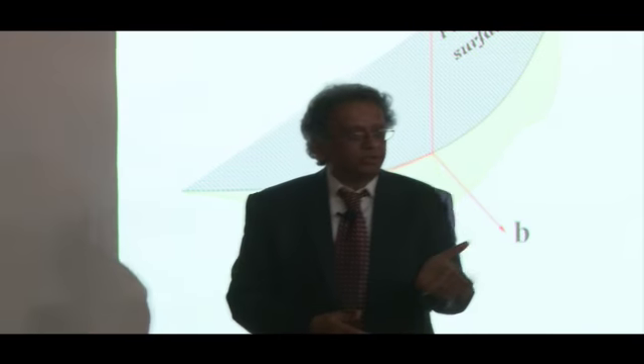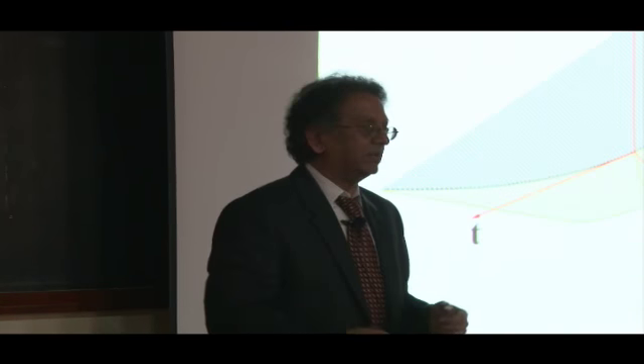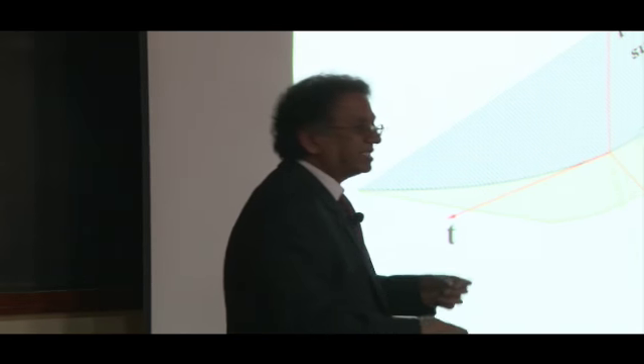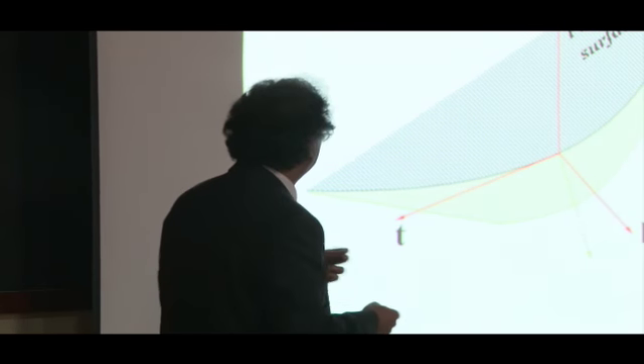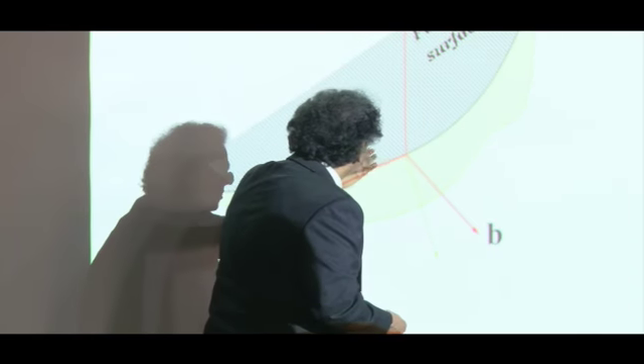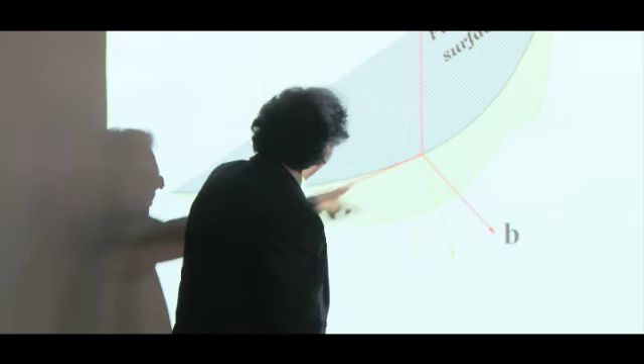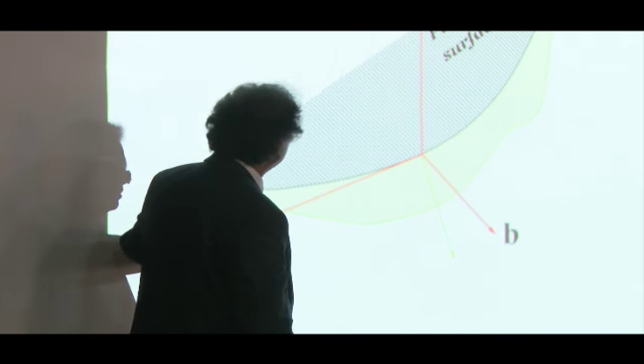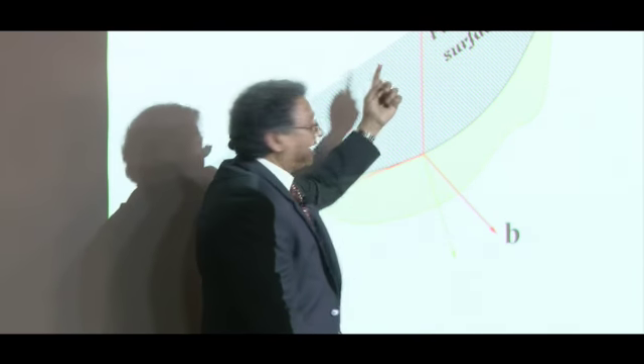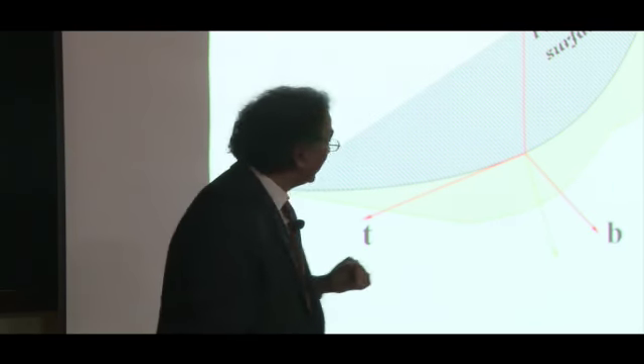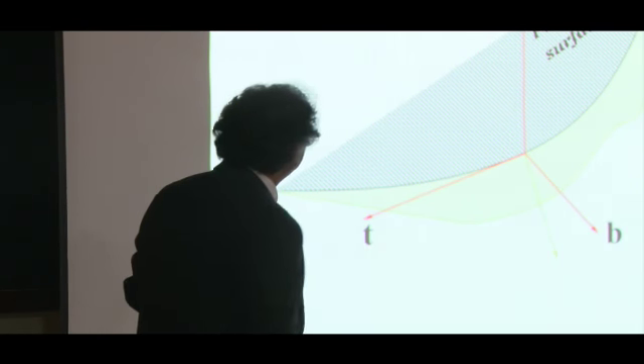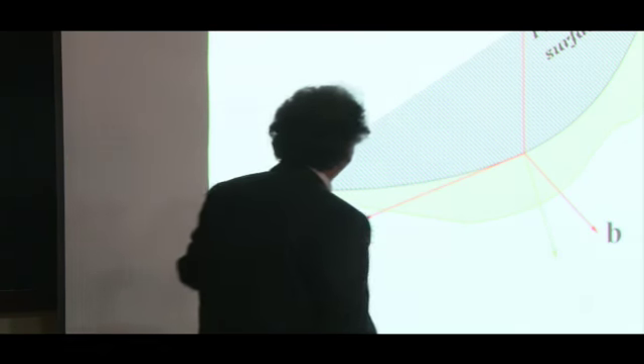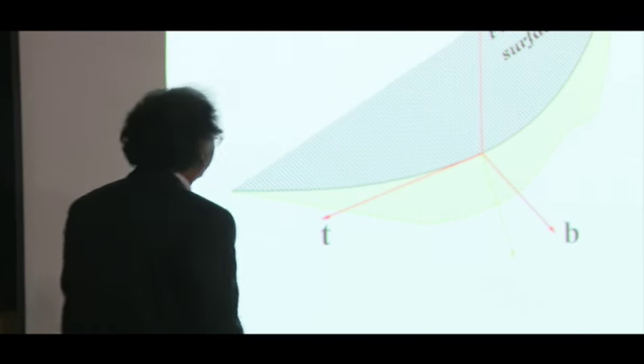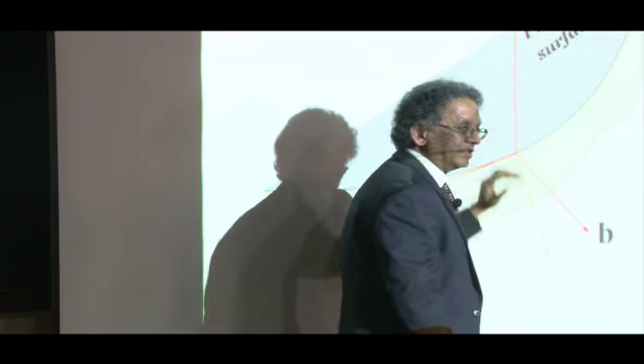Now you can think of three symmetries. This is the plane of the crack. If the loading is perpendicular to the plane of the crack in the N direction, this will be called a mode 1 or an opening mode. If the forces are in the B direction, this is a shearing mode, where the crack is being sheared parallel to itself, and this will be called in-plane shear. And the last one is when the forces applied are in the T direction. This is called anti-plane shear, or mode 3. And in each one of these, the crack does something different.